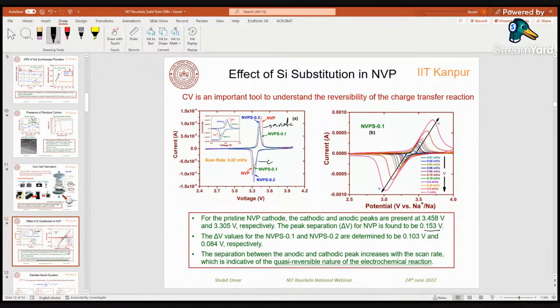That is what we want: the polarization losses should be less and the material should be more towards the reversibility region. We have performed the CV at different rates, and you can see that the peak intensity increases with the increase in the scan rate, and also this gap increases. The increase in the gap basically means that we are in the quasi-reversible region. That means the electrochemical reaction occurring at the working electrode is quasi-reversible in nature. It's not completely reversible and it is not completely irreversible.